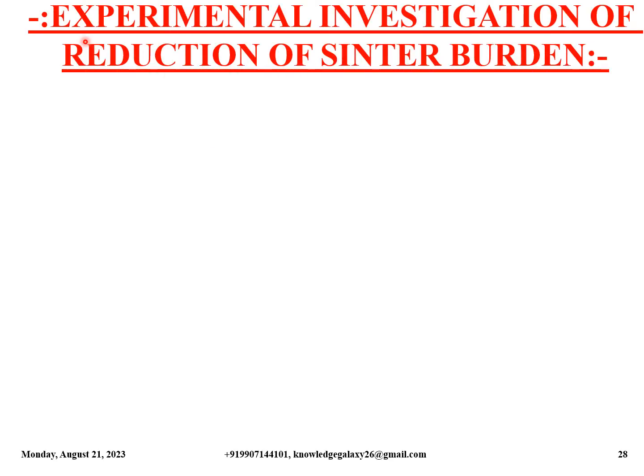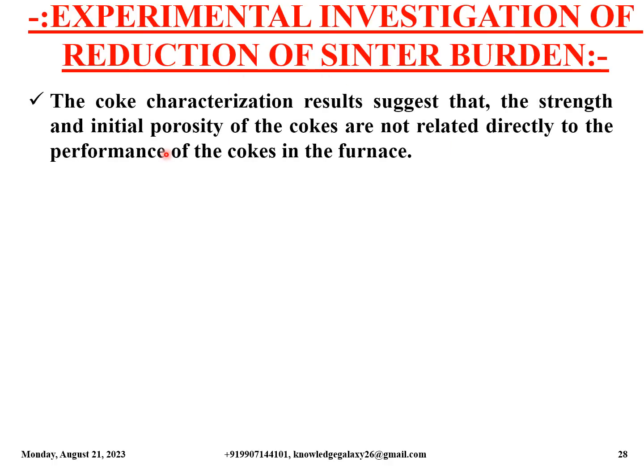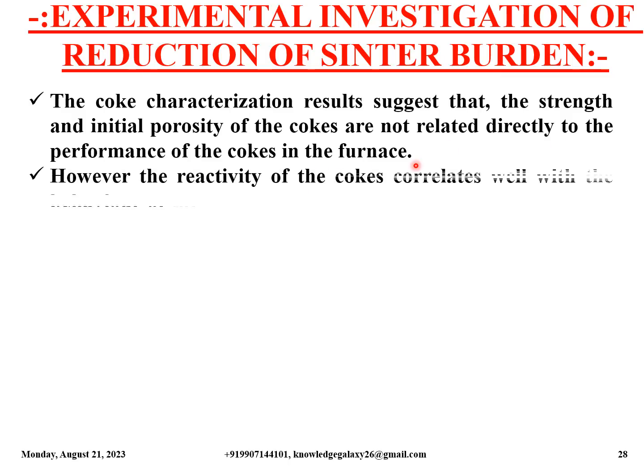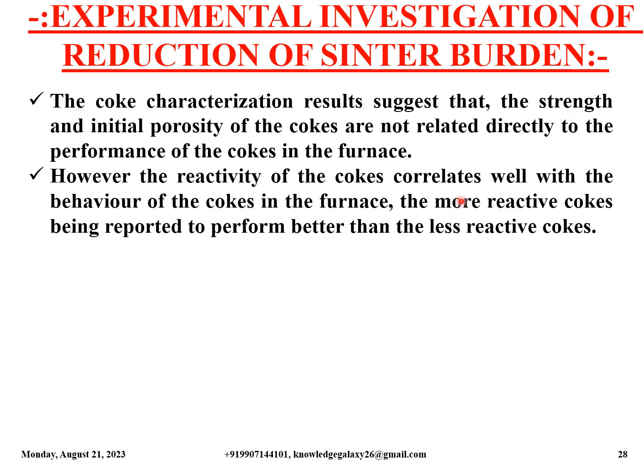Now I am going to explain the experimental investigation of reduction of sinter burden. I hope I am going so far so good, and whatever matter I have discussed is clear to you all. The coke characterization results suggest that the strength and initial porosity of the cokes are not related directly to the performance of the cokes in the furnace. However, the reactivity of the cokes correlates well with the behavior of the cokes in the furnace, the more reactive cokes being reported to perform better than the less reactive cokes.